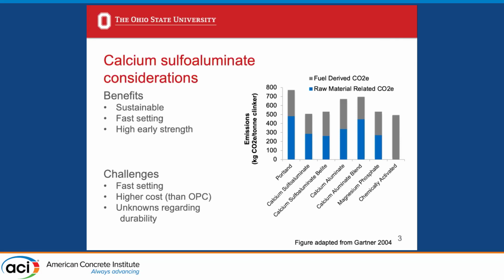There are a lot of challenges associated with this material because it's not been used as prevalently as OPC, so we don't have that giant knowledge bank in most of them. And some of the challenges are associated with that fast setting benefit that we've just talked about, because it can become an impediment to construction. If you have to get your concrete from a batch plant to a site, you're going to need more than 5 to 10 minutes to do that.